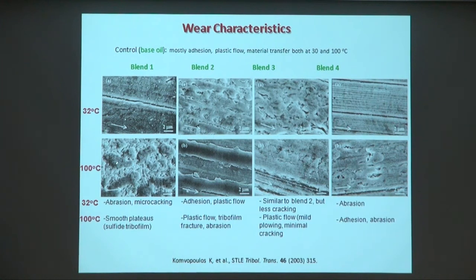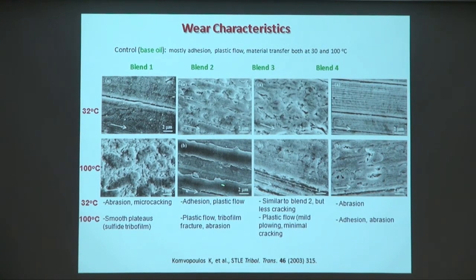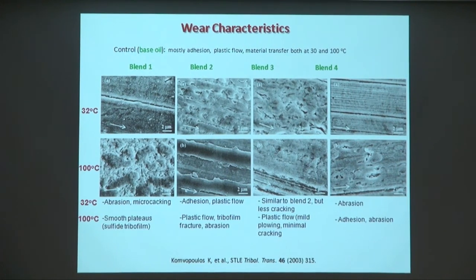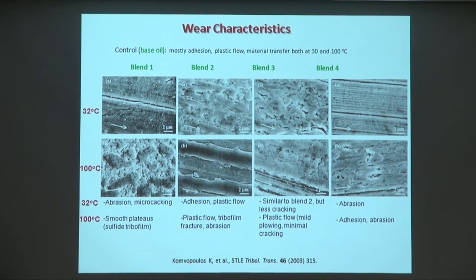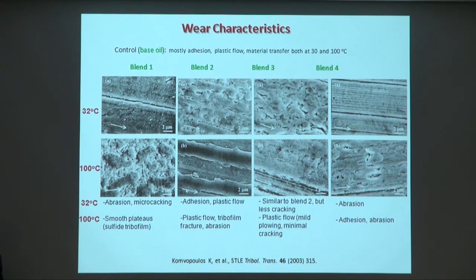For example, here we can see a film that has formed and actually has confined rubbing only at its higher peaks. These are the highest islands. You can see the rubbing process that has changed their color, but is protecting the surface, as opposed to this film that is too brittle. The formulation that was used here was producing a brittle film that is breaking off, but if this exposed metal rapidly reacts with the additives to reform it, as happened here, then that can also be a possible solution that we can accept.